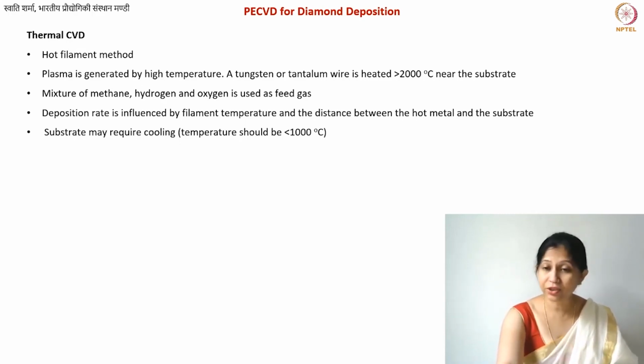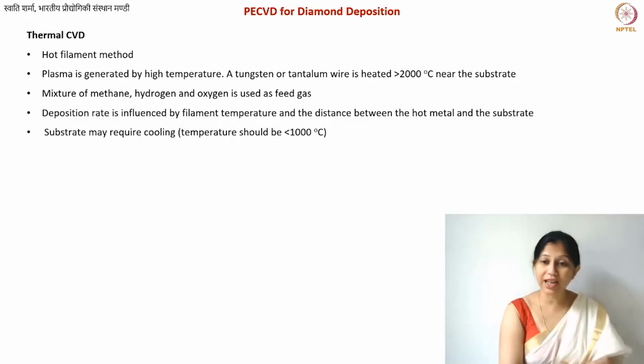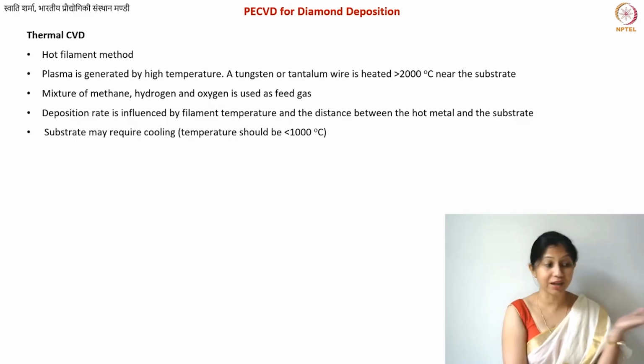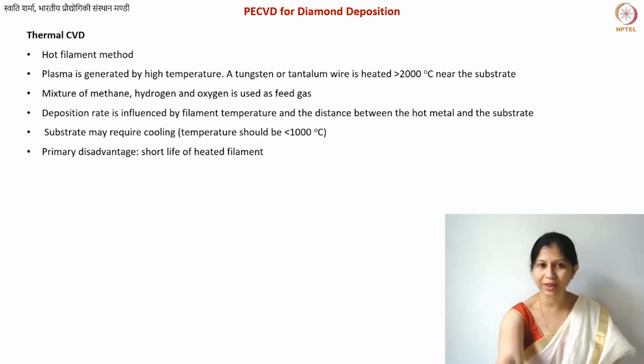The substrate in general may require cooling. One interesting thing now is that you have very high temperatures very close to the substrate. You have about 2000 degrees very close to the substrate, but your substrate should not be above 1000 degrees, otherwise your diamond films may convert back to graphite. So you are going to need some sort of water cooling or any other cooling system for cooling your substrate separately in order to maintain its temperature below 1000 degrees.